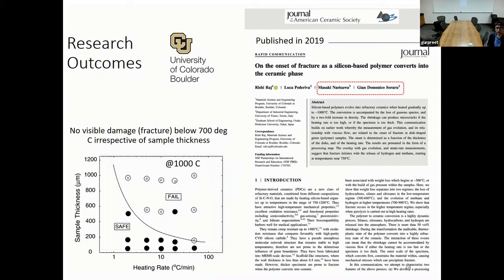In this work, Rishi and his colleagues from Japan and Italy, who are partners, created these fail-safe maps for PDC. They would make PDC samples of varying thicknesses and heat them to different pyrolysis temperatures at varying heating rates. This is the data where the y-axis is the sample thickness and the x-axis is the heating rate, and you see that samples thinner than 200 micrometers never fail. They're not affected by the heating rate. And those that are close to 1 millimeter fail no matter how slowly you heat the sample. That's kind of interesting.